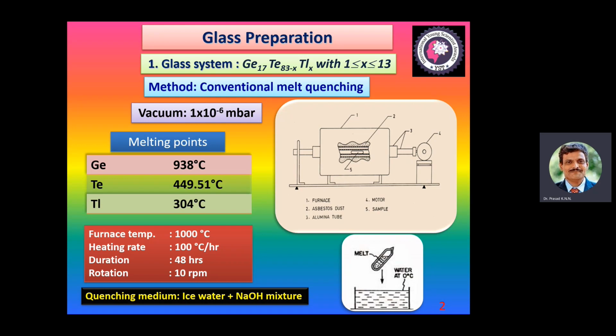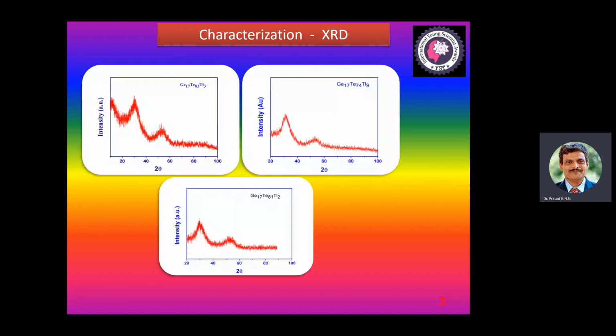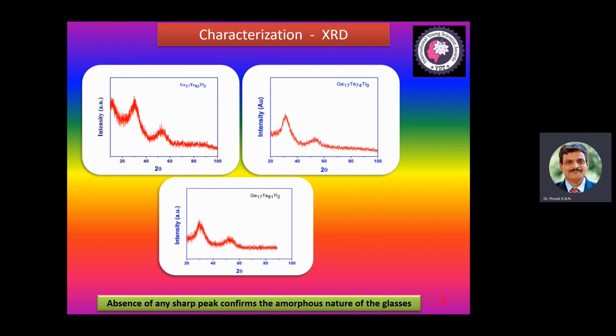In order to ascertain whether the obtained bulk material is a glass, we went for characterization, which is X-ray diffraction studies. We took a few samples as representatives of the series, and you could notice that no sharp peaks are observed in the XRD spectrum, so it is very clear that this material is amorphous. And the amorphous nature is the nature of glass. So it is very clear that the bulk we prepared is a glass. This is how a bulk glass material of germanium, tellurium, and thallium is prepared with conventional melt quenching, and the characterization is done with X-ray diffraction.